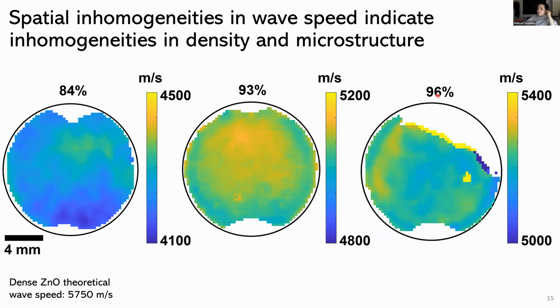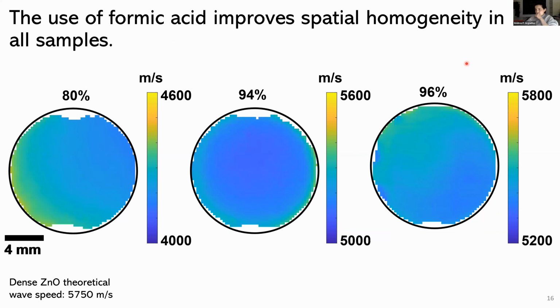And the other thing that we noticed is that because we were using geometric relative density values, a lot of times we were missing the fact that for some of the larger samples, there were actually large laminations that we get direct reflections from. So as I said before, this is already quite informative in the context of what was happening in the sintering process and some of the changes and modifications that we could make to the processing so that we could obtain more uniform samples.